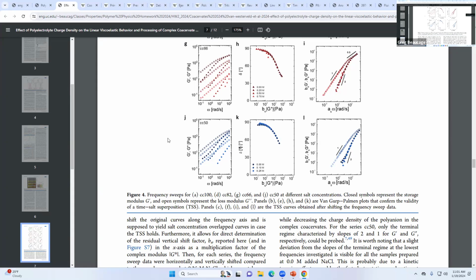So what she says in this paper is that, because I see this behavior in temperature that I could shift, but here I have a dependence on salt, I can use the salt concentration as a shift factor too. So she comes up with a shift factor, mimicking this time temperature superposition, but we're using salt because salt has the same effect. It just shifts the curves. And she says she can use that to get a master curve. And because she can do that, and this middle one is that master curve, it's the same mechanism. She's just tweaking it.